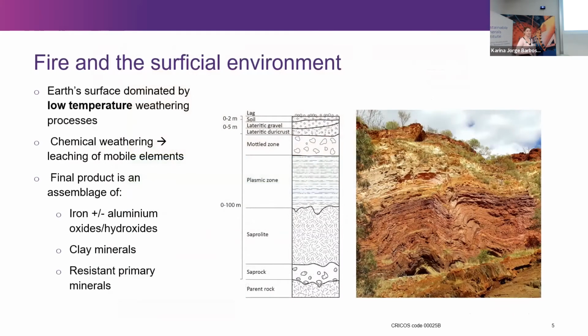So in the surficial environment, as I mentioned previously, it's dominated by low temperature processes. And what's happening in the surface normally, absent of a fire, is chemical weathering, where our fresh rock that's exposed to the atmosphere and to water is weathered, and it's leached of all of the mobile elements. And the end result of this is a nice weathering profile where we see minerals like iron oxide, so things like hematite and goethite, aluminium oxides, if there's enough aluminium in your country rock. So things like gibbsite, clay minerals, so things like kaolinite, illite, smectite, and any resistant primary minerals. So those are things like quartz, titanium oxide, zircons that are left behind and can't be weathered.